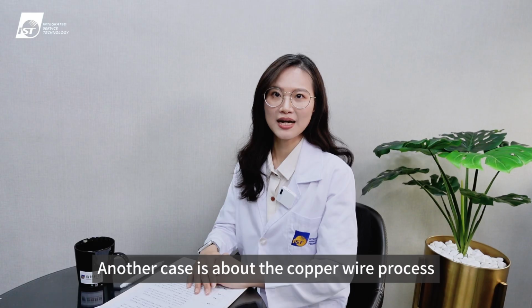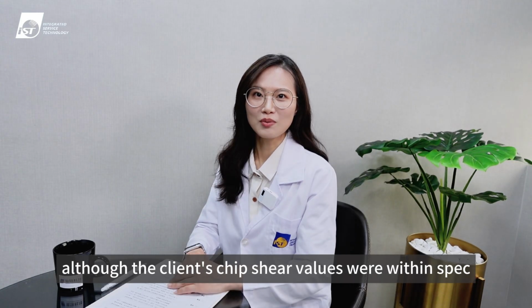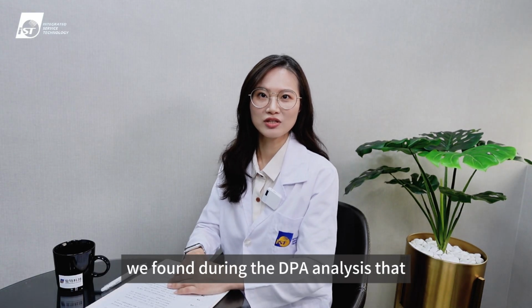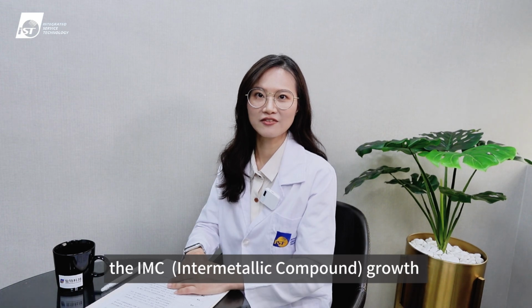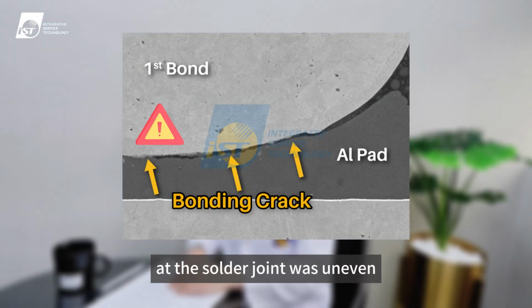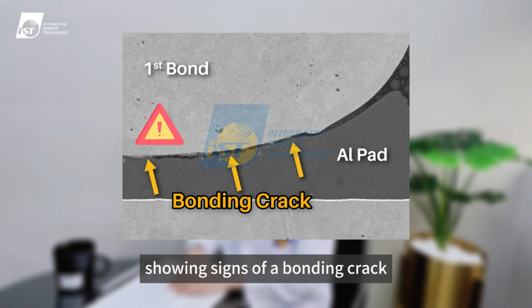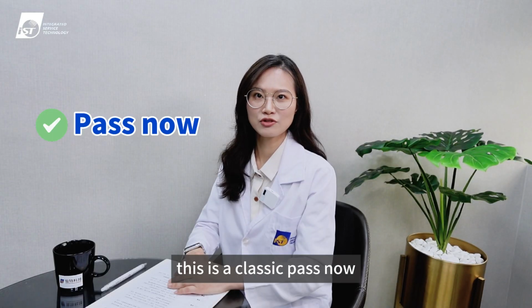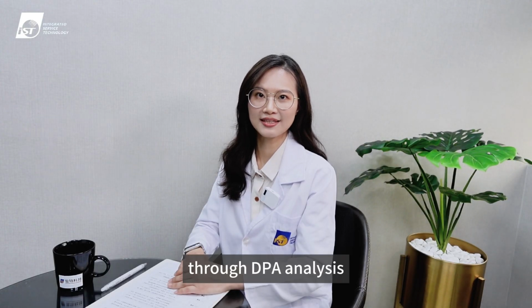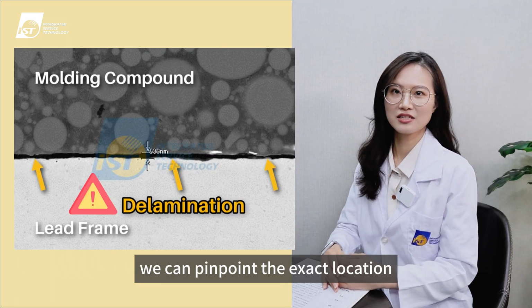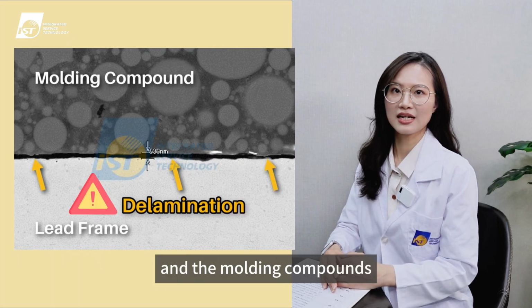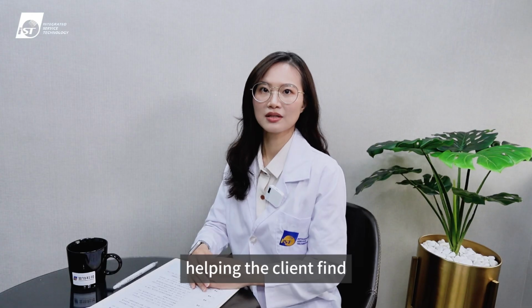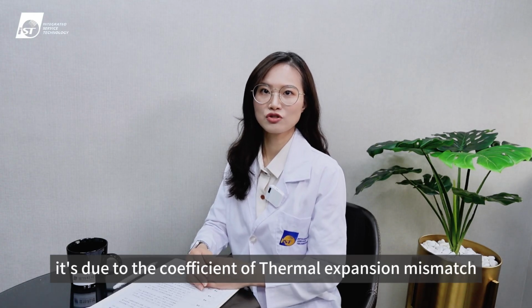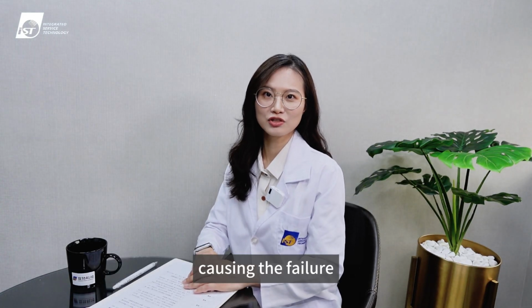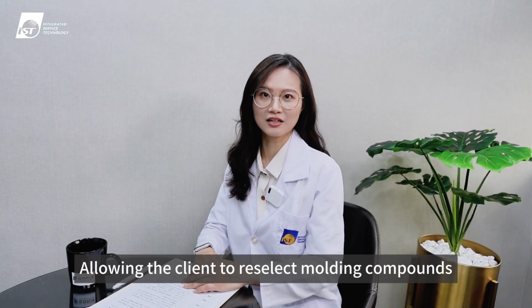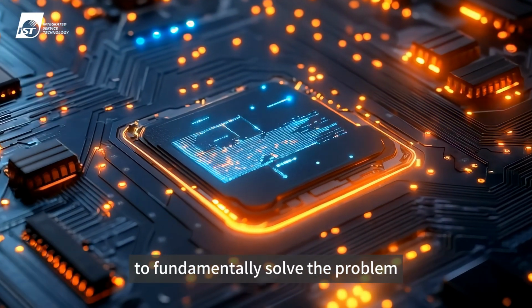Another case is about the copper wire process. Although the client's chip shear values were within spec, we found during the DPA analysis that the IMC growth at the solder joint was uneven, showing signs of a bonding crack. This is a classic pass now, fail later illusion. Through DPA analysis we can pinpoint the exact location of the lead frame and the molding compound's delamination issues, helping the client find it's due to the coefficient of thermal expansion mismatch causing the failure, allowing the client to reselect molding compounds to fundamentally solve the problem.